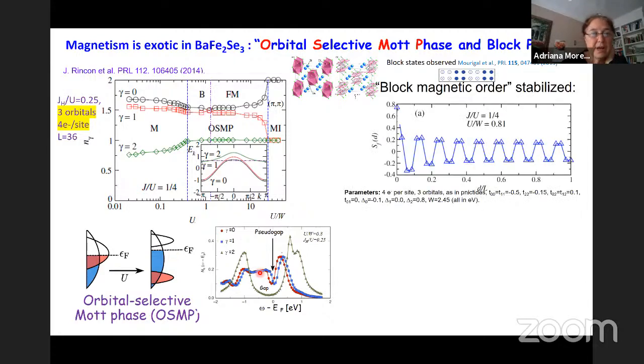In addition, we looked at the magnetic order in this region that we call B, because we observe blocks. We found that nearest neighbor spins align ferromagnetically, and they form blocks that are antiferromagnetically aligned with each other. This is like the 1D version of what Mourigal et al. observed experimentally in the ladder material.